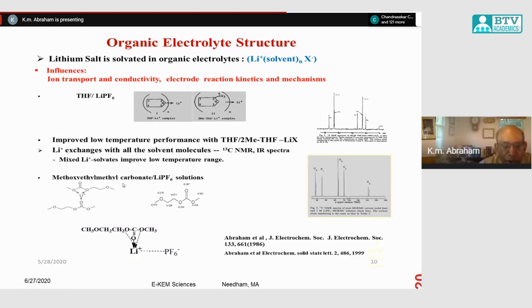This is another electrolyte that we showed, where the solvent has both a carbonate moiety as well as an ether. So this methoxyethyl methyl carbonate has both, and we showed from NMR studies that the lithium is complexed with the carbonate part, preferentially to the ether part of the carbonate solvent. So those are some of the basic studies that you can carry out on the electrolyte. We published these papers in 1986 and 1999 in the Journal of the Electrochemical Society.